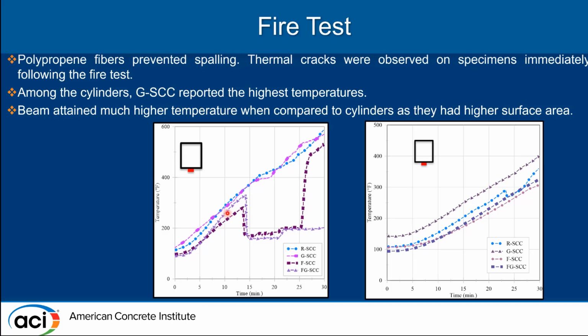Research says that at approximately 320 degrees Fahrenheit, polypropylene melts inside the concrete matrix, and as it melts, it tends to create voids within the matrix. These voids help in release of the pore pressure that is caused during the heating of the concrete. And due to this, these polypropylene microfibers help us in avoiding any kind of spalling.